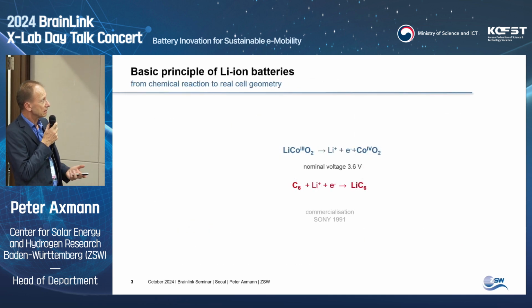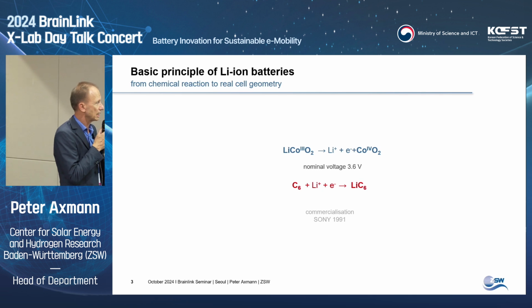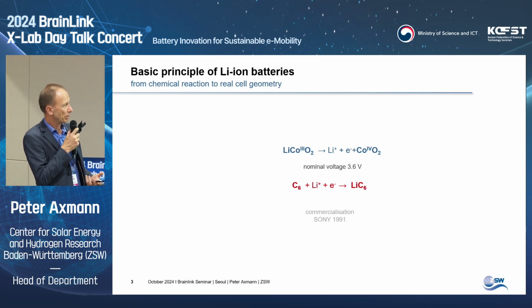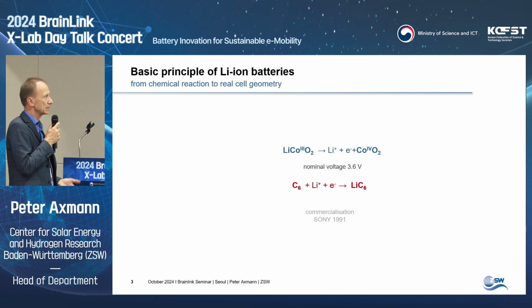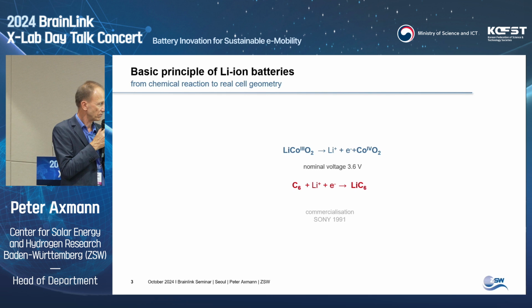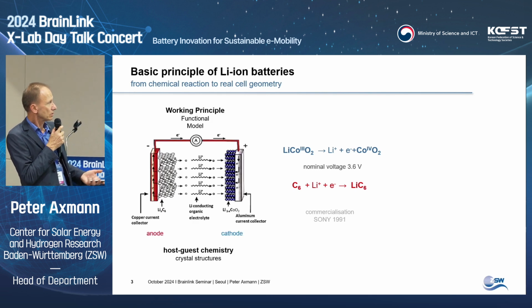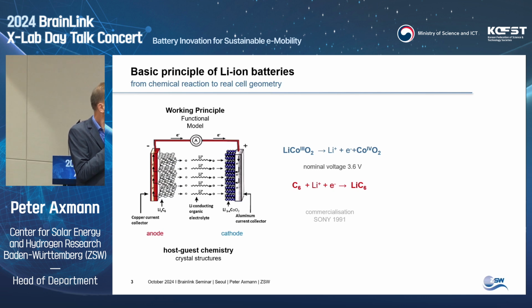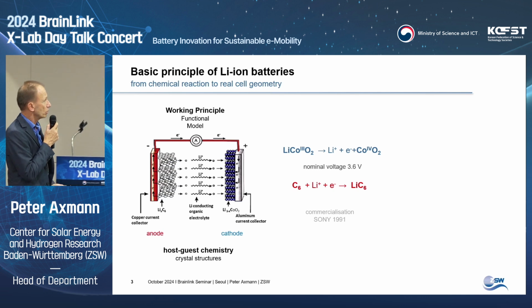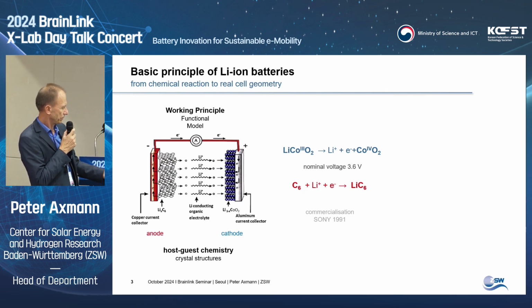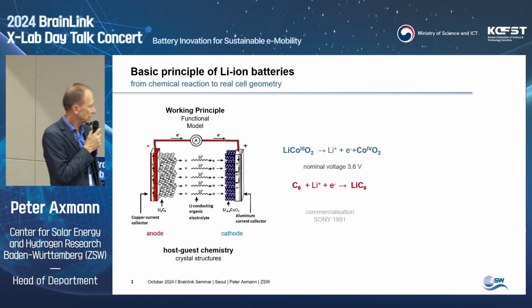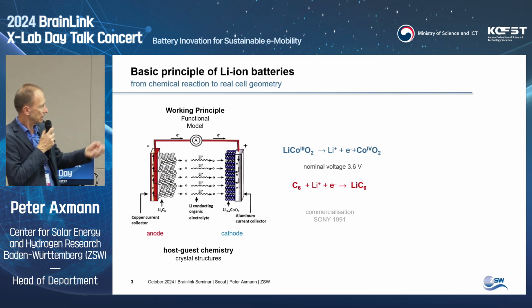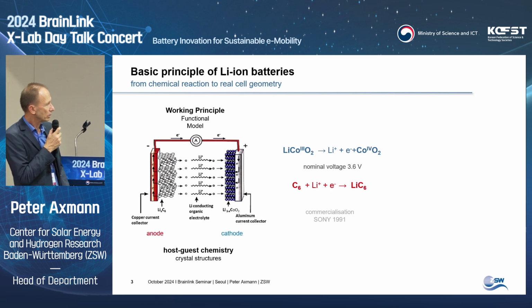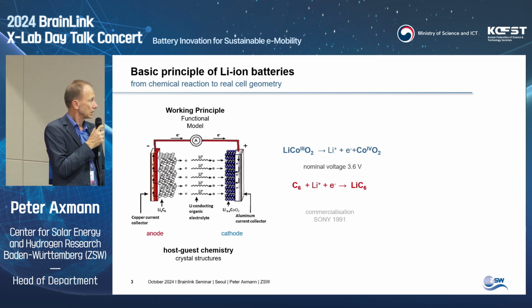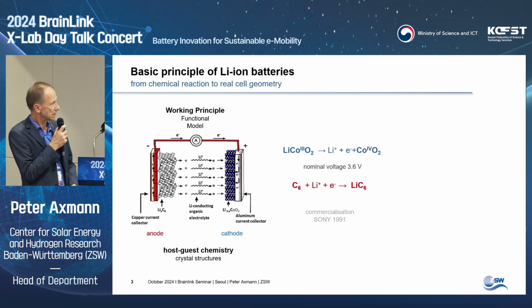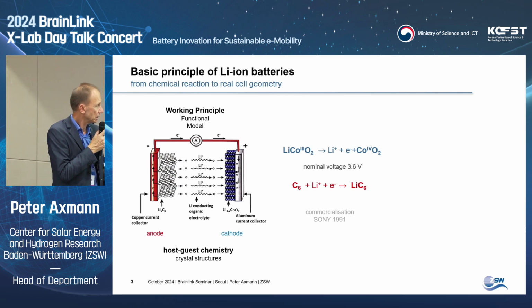So the basic principle of lithium-ion batteries has been commercialized by Sony in 1991. They used lithium cobalt dioxide as a positive electrode material, graphite as the negative. This cell had a nominal voltage of 3.6 volt. And so these materials are more or less a prime example for host-guest chemistry applied in technology. So the working principle is shown already here. We see on the left-hand side the negative electrode, where the electrons come during operation from the lithiated graphite, go through the outer current circle to the positive electrode and are reduced there at the cobalt oxide. So lithium moves through the internal part of the cell to maintain charge neutrality.